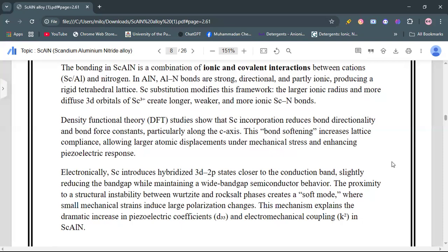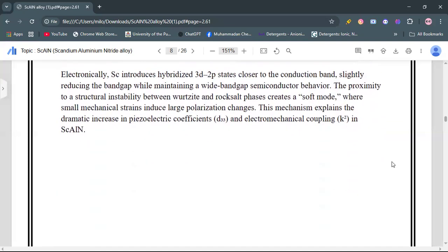Electronically, scandium introduces hybridized 3d-2p states closer to the conduction band, slightly reducing the band gap while maintaining wide band gap semiconductor behavior. The proximity to the structural instability between wurtzite and rock salt phase creates a soft mode where small mechanical strains induce large polarization changes. This mechanism explains the dramatic increase in piezoelectric coefficients, which is represented by d33, and electromechanical coupling in scandium aluminum nitride.